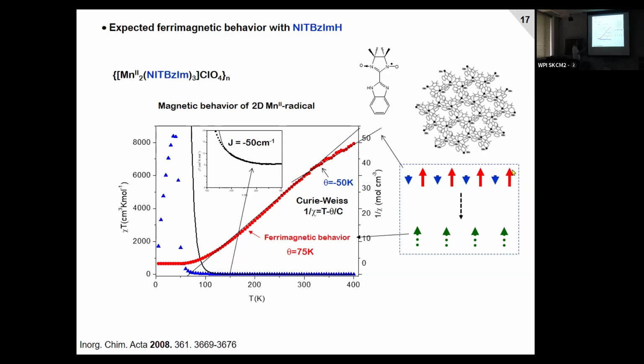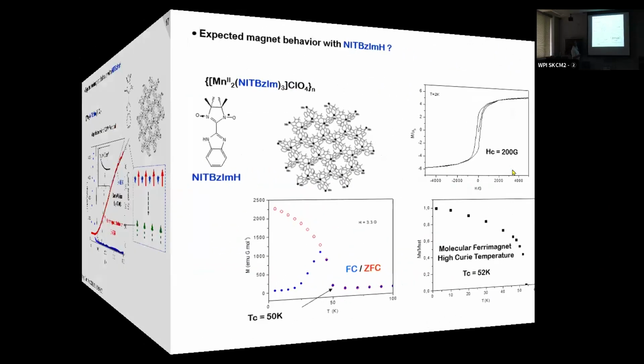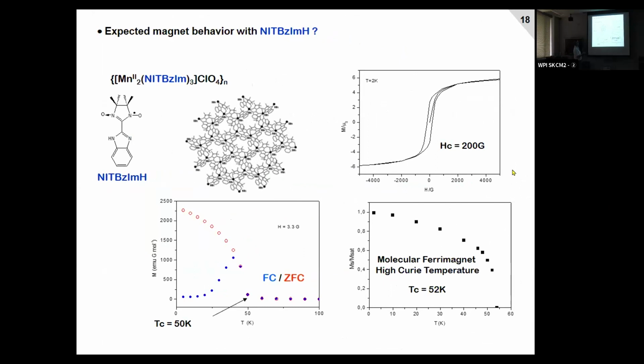So it is why now you see this second behavior. The first one we use for the temperature in negative temperature, and the second was the temperature axis in positive temperature, so ferrimagnetically. So you see the ferrimagnet, so you have an alternance of manganese 2 and radical coupled anti-ferromagnetically. And this behaves like a magnet. At low temperature, we can see there is this loop. And if we study the magnetization versus temperature, the zero field magnetization, we can reach the Curie temperature, which is about 50 Kelvin. And you have the same value if you draw the magnetization versus magnetic field.